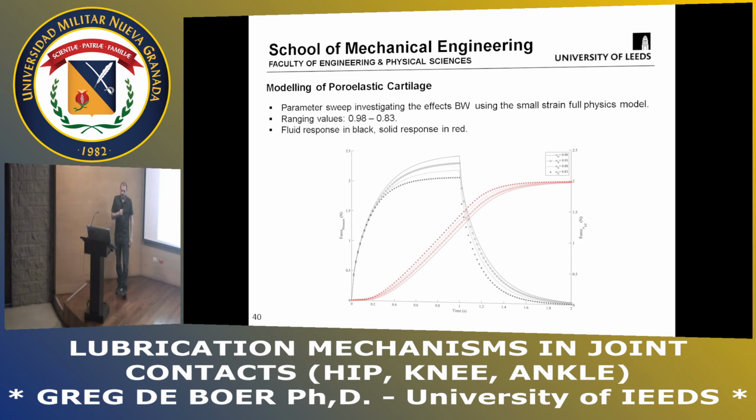Okay? So here, we compress our material and hold it. And what happens is the fluid responds really fast to that load. The solid takes some time to build up. And actually, the peak pressures that you obtain are quite different if you do include these extra terms.